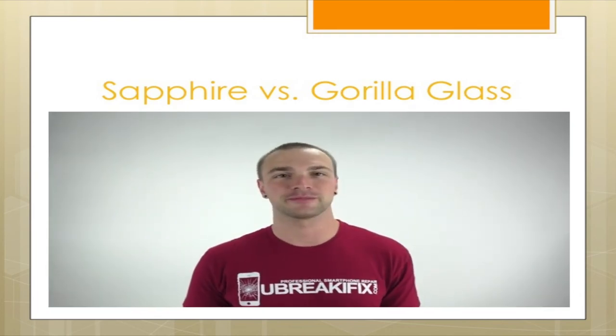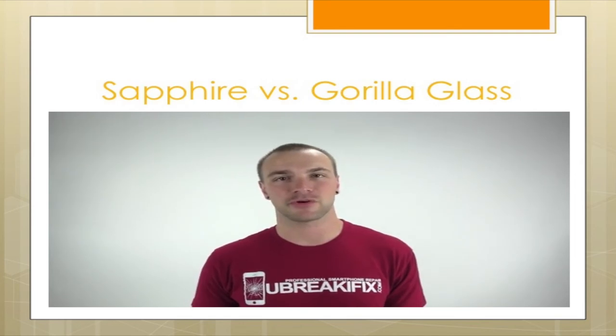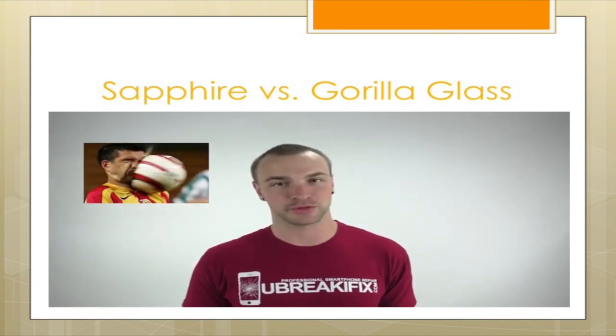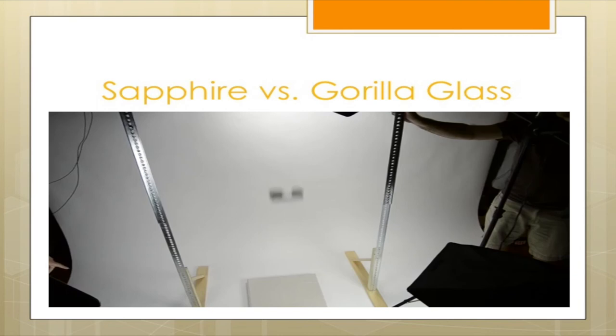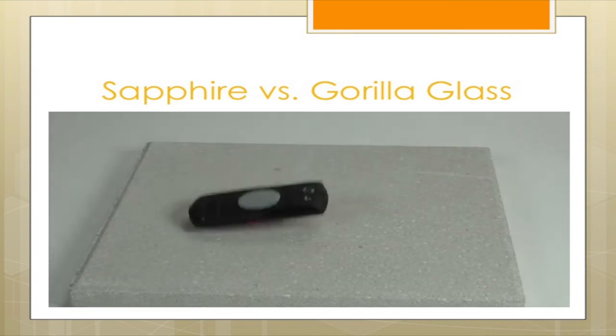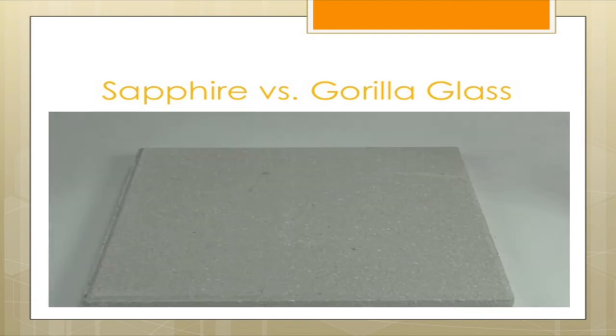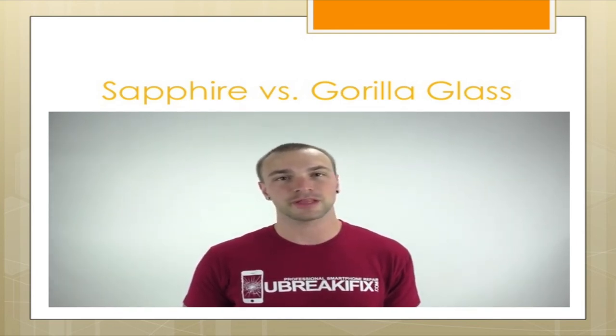So what does it all mean? It means yes, Sapphire is a bit stronger than glass, but because of its brittleness, we don't think there'll be a net benefit to using Sapphire over glass in terms of impact resistance. And that's really what matters. If you take a look at our video on the Kyocera Brigadier, which has a Sapphire display, without the phone's strong bezel, the glass breaks on its first drop of just 3 feet. So what we can say is, Sapphire alone will not likely be more durable than Gorilla Glass, but instead it's the phone and the other features which will help protect it.